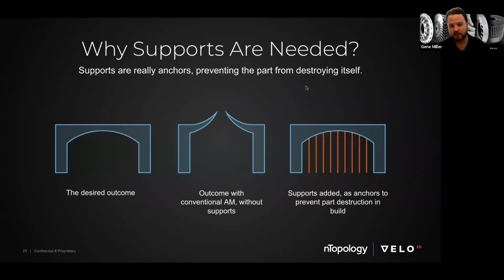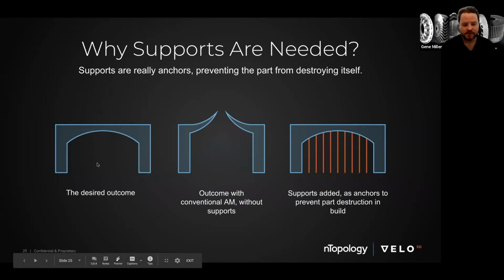So in a conventional metal AM system, these challenging features that we have to overcome are supported. Supports are not there to prevent the part from collapsing or anything. They're actually there to keep things anchored down and constrained so that the internal stresses that are developed during printing don't cause deleterious warping and movement of the parts. If you look at the desired outcome on the left here, this is essentially what we would want to print, but without any support material, these overhangs tend to warp upward and can tear themselves apart and cause recoating to be impossible.